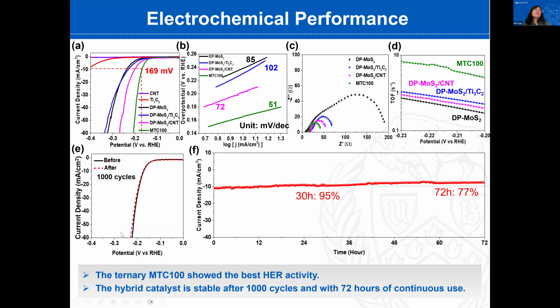So the stability evaluation is conducted here. So we recorded the LSV curve before and after one thousand cycles. And what we found is that the material performed quite good stability, and it is still maintaining 77% activity after one thousand cycles with 72 hours of continuous use.